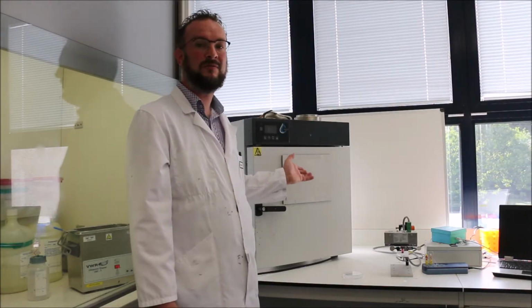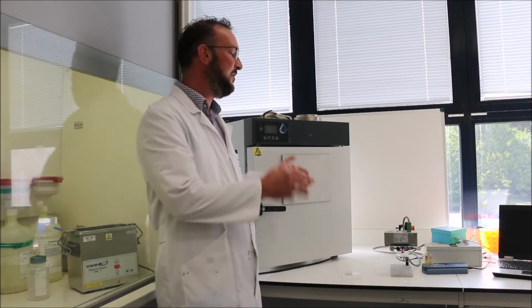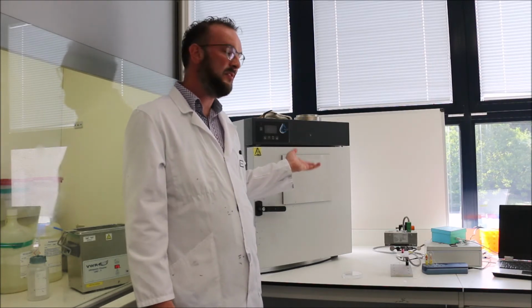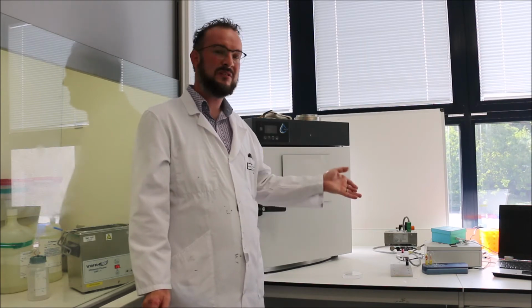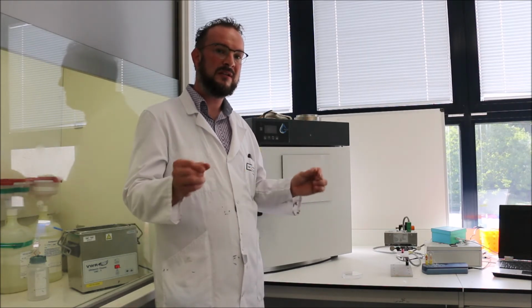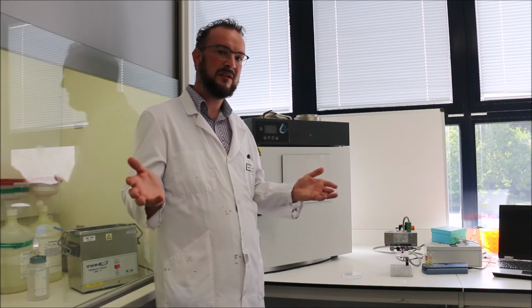So here you see the oven and a near-infrared sintering system, and we use these systems to cure our printed samples. If, for example, you print silver-based nanoparticle inks, you need the oven to go to 250 to 300 degrees centigrade. This means that for samples that are heat sensitive, like textiles and paper, you cannot use this oven, and we investigated the use of near-infrared sintering on these heat-sensitive substrates. Because with this system, you heat up only the printed lines and not the surroundings, such that your textile and your paper will not degrade.